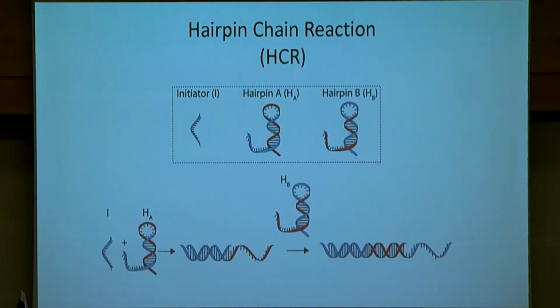Now, it is not easy to place a thin film of hydrogel on an electrode, and I think that here we have developed a very unique method. This is a versatile and generic method that is based on the so-called hybridization chain reaction. Now, the hybridization chain reaction is a process where we take a promoter unit, a promoter nucleic acid, and two hairpin structures. The promoter opens hairpin A. Once we open hairpin A, the open stem region opens hairpin B, and the open hairpin B opens back hairpin A, so we can generate long polymer chains of hybrids that contain this duplex nucleic acid.